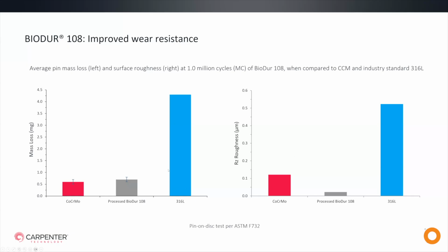As you see on these slides here, the actual results that we're sharing, BioDur 108 demonstrated comparable mass loss and surface roughness to the cobalt-chrome molybdenum, even under a rather aggressive 1 million cycles on a pin-on-disc test. So this means that it may be a viable alternative to cobalt-chrome.